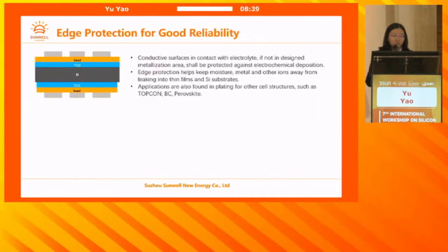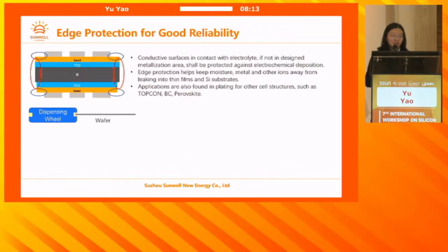For the edge protection, it's necessary to achieve good reliability, because basically all the conductive surfaces in contact with electrolyte, if they're not meant to be your metallization patterned area, should be protected. It also helps to keep moisture, metal, and other ions away from leaking into thin films and silicon substrates. So the edges and surfaces have to be protected. Our method is that we have this dispensing wheel, and the liquid resist goes from the center and dispenses to the edges. Any part of the dispensing wheel will never touch the wafer. It's only the resist material touching the wafer.